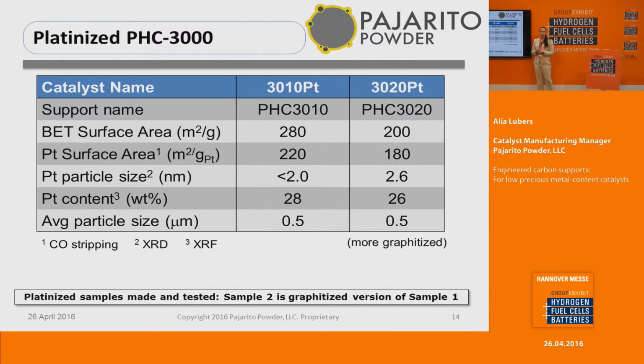So I've mainly been talking about our support itself. It's mainly carbon and graphitic carbon with a little bit of metal and some nitrogen. In order to evaluate these materials for fuel cell catalyst supports, we need to put platinum on them. So we've developed platinum deposition methods as well as in-house testing, in addition to getting some assistance from our partners. In this particular case, we sent 2 different types of support to our partners, and they deposited platinum. Our PHC 3010 is a less graphitic material, and our 3020 is a more graphitic material.